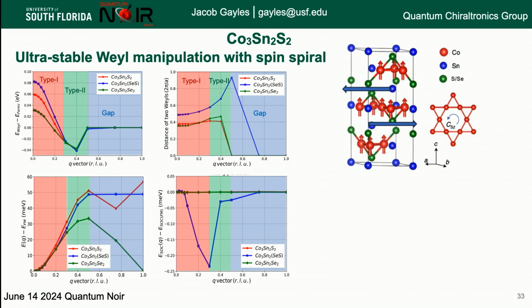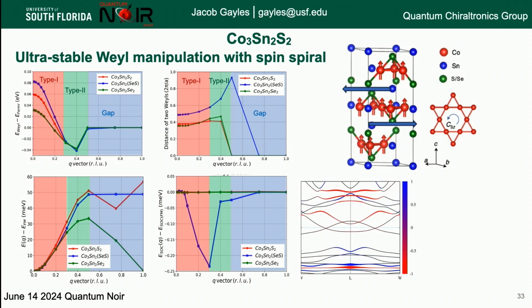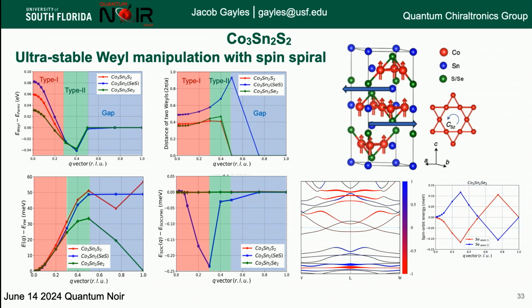So then we said, okay, maybe the DMI is changing layer by layer. So we had to write some new code to look at it layer by layer. And in the end, when we looked at it layer by layer, what happens because of the characteristics of those Weyl points, they suppress any energy that will give rise to the DMI, which is this DMI energy for each of those bands. And what you see actually is that it changes sign on both layers, and so then that also cancels it out. Still not enough to stabilize skyrmions. And so what we're working on now, which I don't show the results because I'm not completely happy with them, but it's actually a second order interaction that happens here that's similar to the DMI that actually stabilizes the skyrmions.